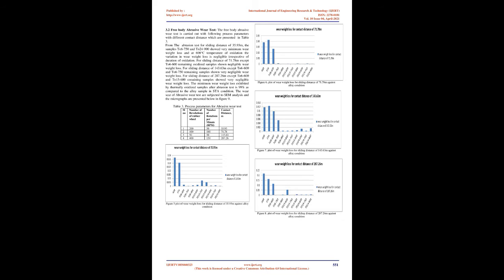following process parameters. 1. Sand flow rate is 60 grams/minute. 2. Load applied is 28.56 N, 3 kgf. 3. Diameter of rubber disc 228.6 mm. The test is carried out for different revolutions of rubber wheel, i.e. for different contact distance to study the wear volume loss at different intervals.